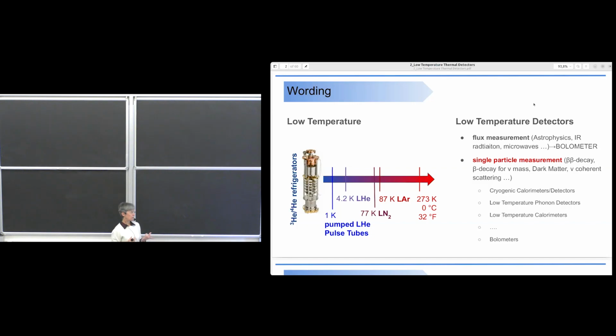And one of the differences between these two kinds of detectors is that when you have a very small thermal detector of a single particle, you can operate it, say, at about 100 millikelvin. That is much easier. While if you want to operate a detector that has the mass of 100 grams or even 1 kilogram, you need to go lower in temperature, therefore at about 10 millikelvin.